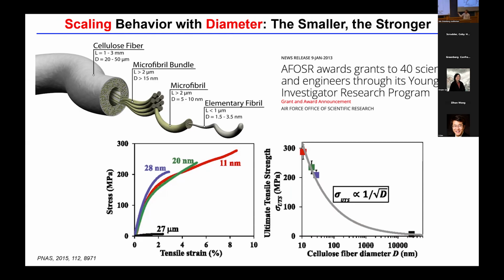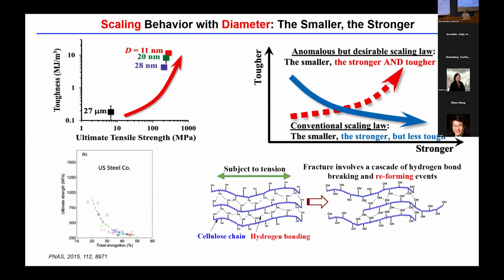So this basically shows that if you make a piece of paper using smaller fibers, the mechanical strength will actually be enhanced, right? You get the so-called smaller, stronger. But you don't lose the ductility. That is very different from metals. Usually when you increase one, you decrease the other. But here you are not losing the ductility. So actually the toughness increased as well. Yeah, so this is very interesting.